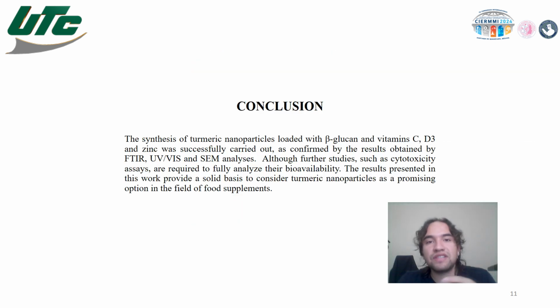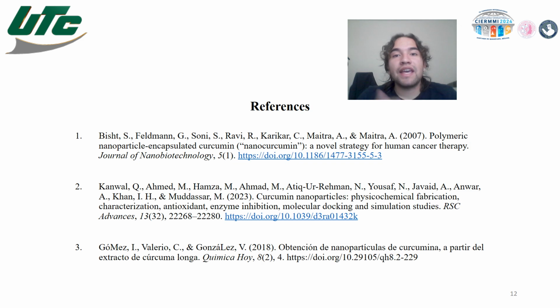In conclusion, the synthesis of turmeric nanoparticles loaded with beta-glucan and vitamin C, D3, and zinc was successfully carried out, as confirmed by the results obtained by FTIR, UV-Vis, and SEM analysis. Although further studies such as cytotoxicity assays are required to fully analyze their bioavailability, the results presented in this work provide a solid basis to consider turmeric nanoparticles as a promising option in the field of food supplements. And that will be all from our side.